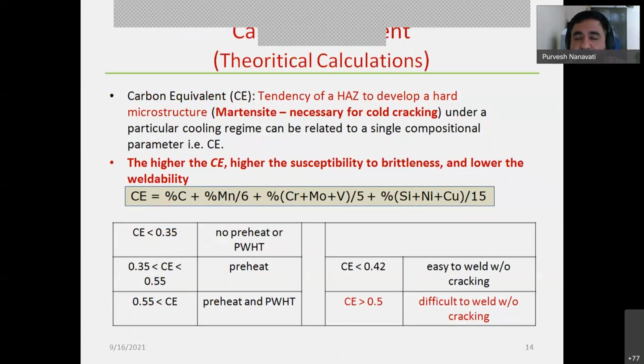So you can see that for carbon steel and low alloy steels, their weldability is judged by an empirical formula. It is well established, known as carbon equivalent. It is a formula reflecting the composition of the steel: carbon, manganese, chrome, molybdenum, silicon, nickel, copper. So you can understand these are the alloy elements having an effect on their weldability.